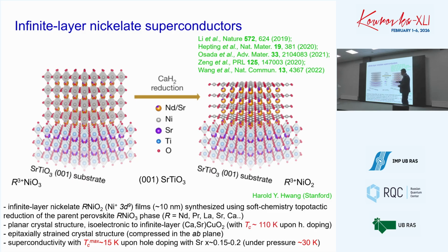This is layer-by-layer growth of the perovskite phase and then a reduction, soft chemistry, topotactic reduction with some chemical substances, where they cut the apical oxygen. This is a very non-trivial technique; to me it is like a mystery that they managed to obtain clean, homogeneous thin films. It was realized that thin films of about 10 nanometers, synthesized with this soft topotactic reduction, show superconductivity.